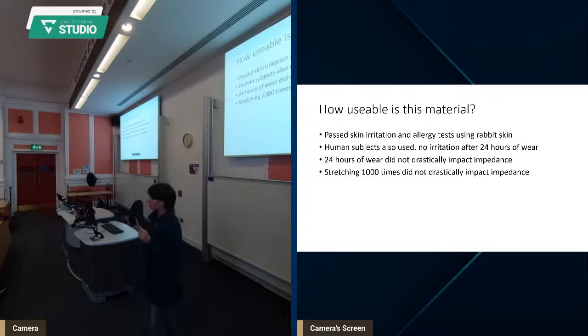Another experiment that the paper did is that they took the material and they literally stretched it and then let go of it 1,000 times. And this also did not drastically impact the impedance.